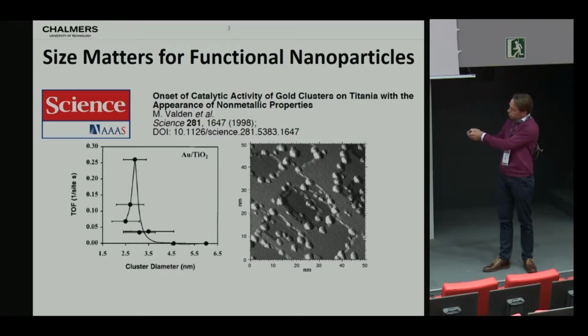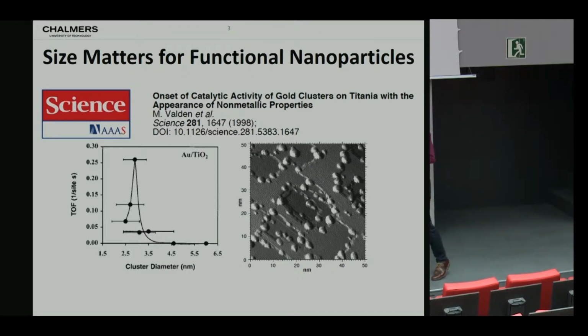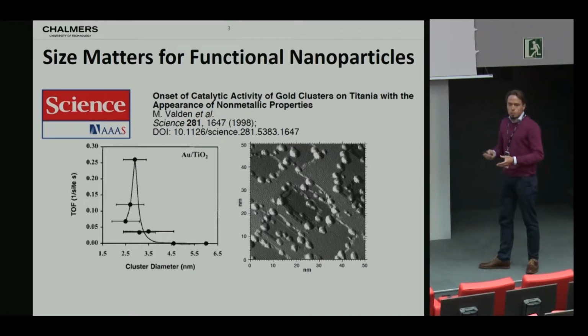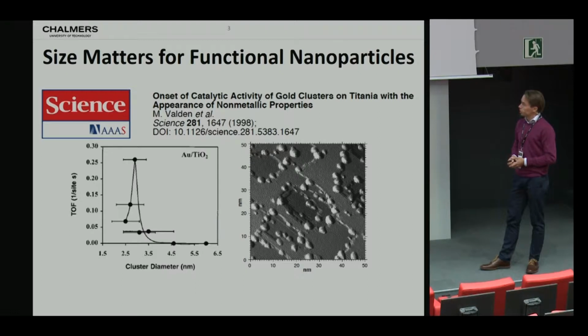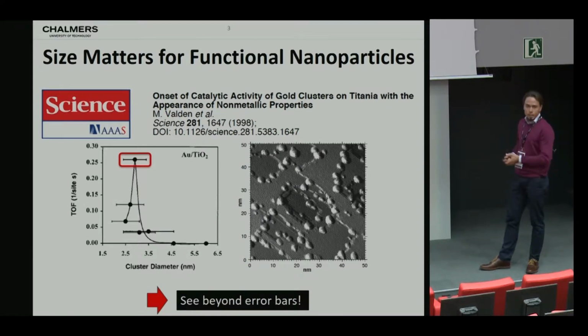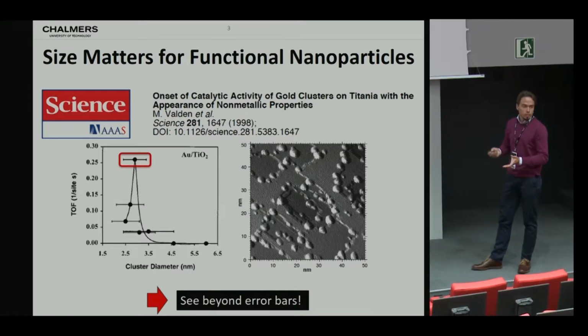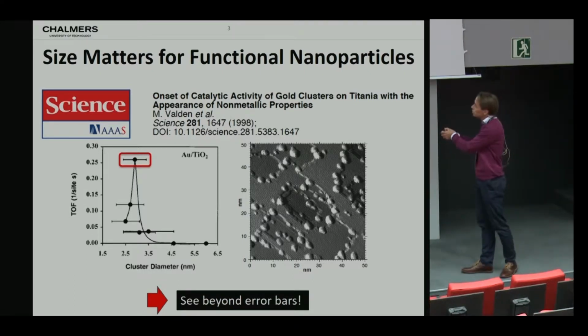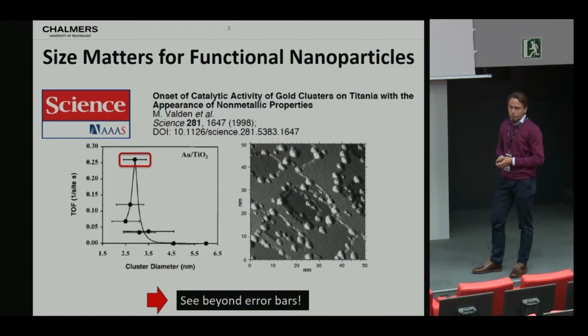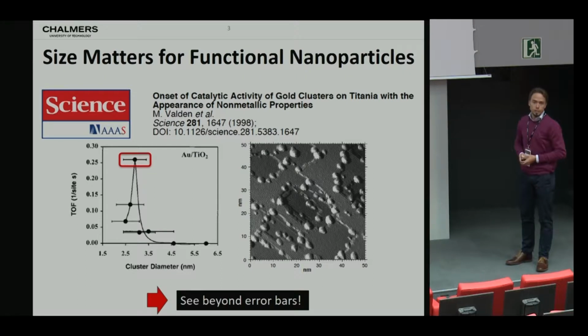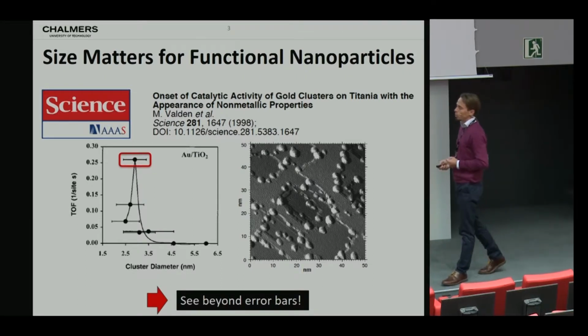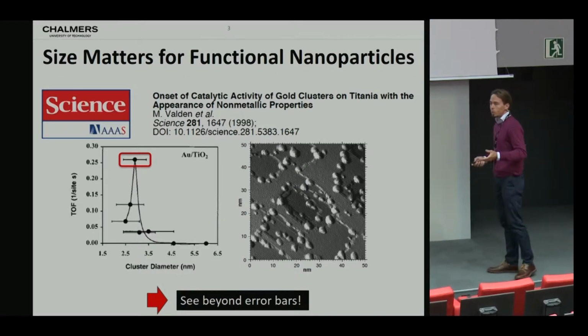But then, as you can see, all of a sudden you have the onset of reactivity, which peaks around 3 nanometers and then goes down again. But you also notice, when you look at the STM image that they take of the particles they used for this study, that they are obviously not homogeneous. And what does that translate into? Well, it translates into this error bar along the size axis. And if we now were able to look at one of these at a time, essentially we would be able to see beyond this error bar, and we might find that there is a specific size where the activity might be a lot higher than what we actually see in that graph. So that's one reason why it is important to attempt to study nanoparticles one at a time.